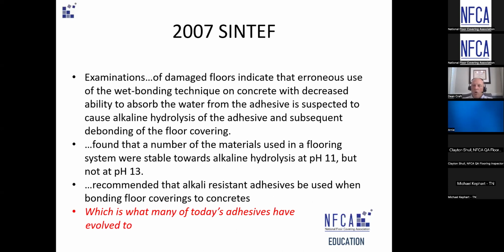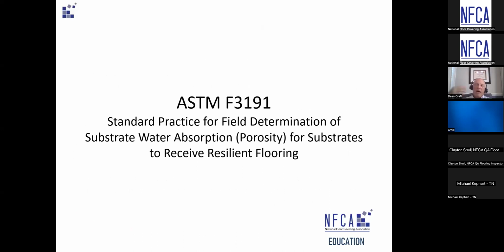So we've evolved, but when we go back to failure analysis of what occurred, we can't go back to history and say the concrete moisture actually didn't cause this failure. It was actually a lot of water in the glue on a non-porous, non-absorbent substrate that caused the damage. But just keep in mind that adhesive selection and substrate absorptivity are critical, and it leads us to F3191.